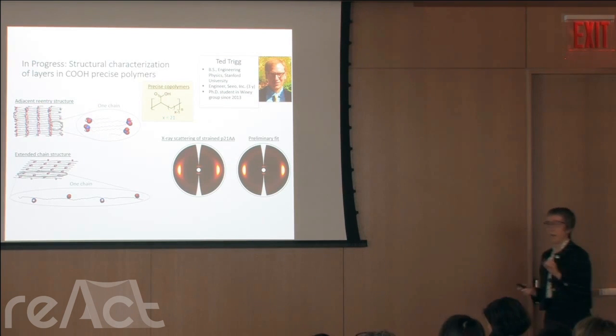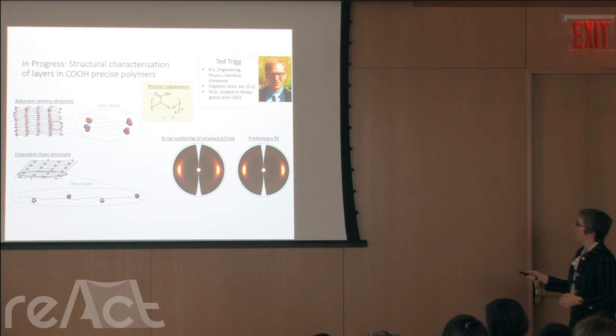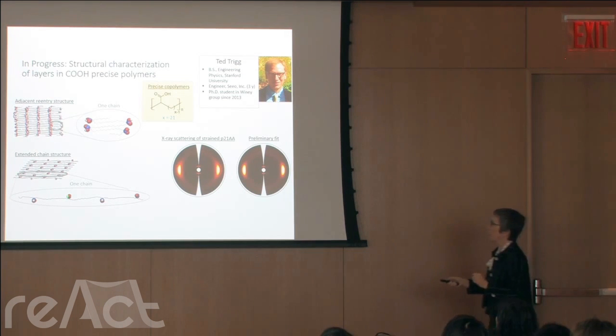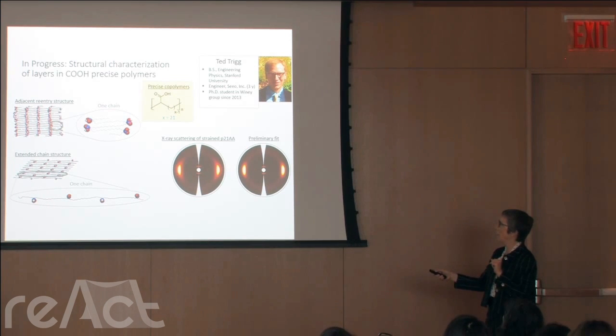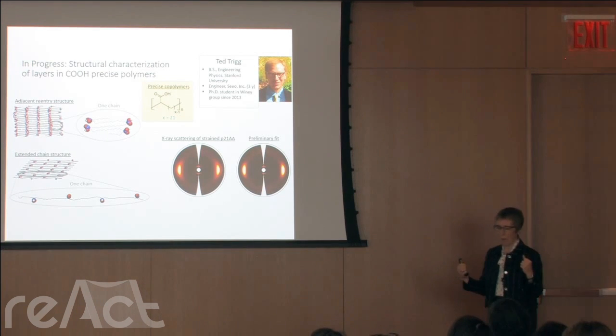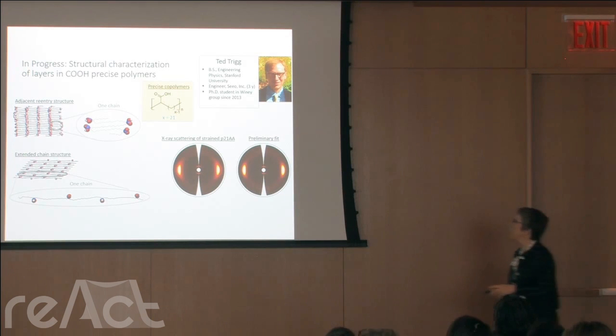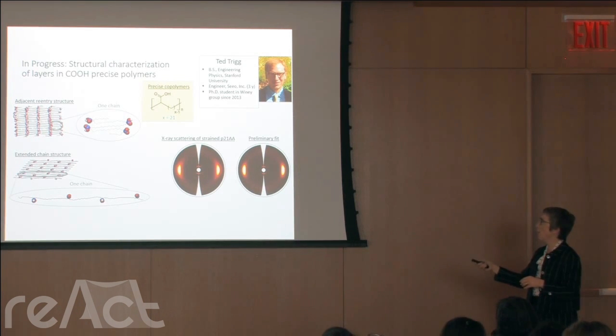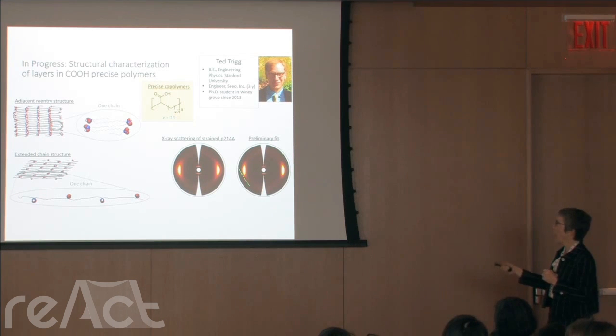One of our fellows for ACT3 is Ted Trigg. And so he's doing some atomistic molecular dynamics simulations to look at these layered structures. We've proposed two different types of structures. This is an adjacent reentry. So this is one polymer chain pulled out of this pseudo liquid crystalline sort of structure, where it zigzags back and forth, dropping off the acid layers here that form these layers. Or we can have an extended chain. So we're looking at these two potential chain conformations for the layered structures. And we can evaluate which structure we have by comparing experimental X-ray scattering data with calculations of what the scattering pattern would be as expected.